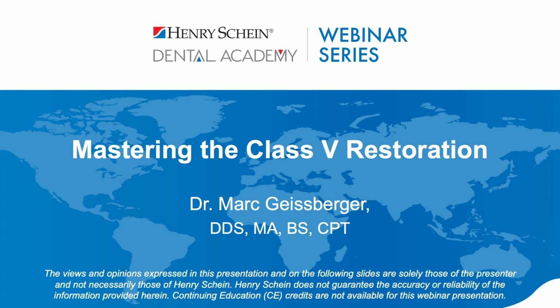Do you prefer composite or any other material if it's subgingival? All right, so you really have to consider what caused the lesion. If it's a carious lesion in a high caries risk patient that has uncontrolled disease, I actually would lean towards a glass ionomer or even a resin modified glass ionomer. However, if the disease is biomechanical from grinding or clenching, if it's from toothbrush abrasion or erosion from acid, I don't have to worry about decay. So that's when I'll default to the use of composite resin.